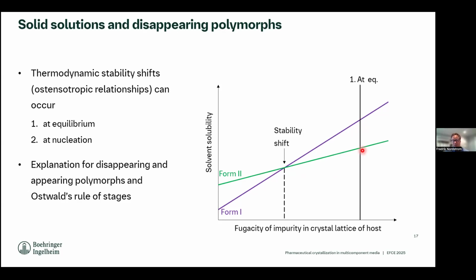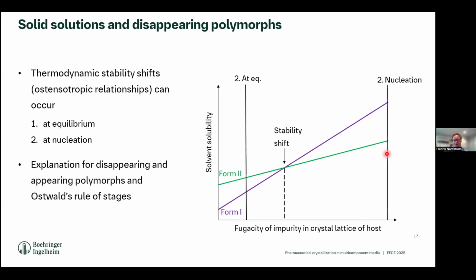But there's also a second way you can do this, right? We saw this example in the 2,3-hydroxybenzoic acid, right? We have a complete thermodynamic stability shift to a different form. But there's also another way you can do this, and that's through nucleation. So starting here, maybe equilibrium is here, but now we're nucleating at a much higher level, and then slowly through solid solution ripening, it drops down to this level. So it's possible, kind of like the Ostwald rule of stages, that you have a nucleation of a form that in that particular scenario is actually more stable. And then slowly, as the ripening proceeds and you're reducing the impurity load in the solid phase, you're again switching the stability. You're crossing this transition point right here, and then going down to the previous relationship. So these can be a thermodynamic explanation for why we see disappearing and appearing polymorphs.